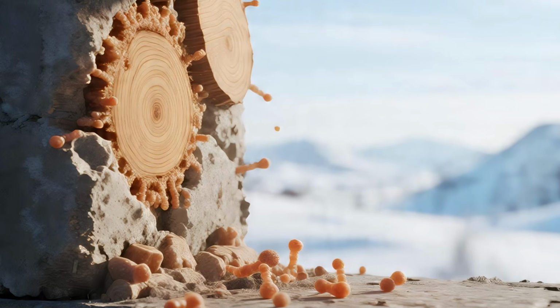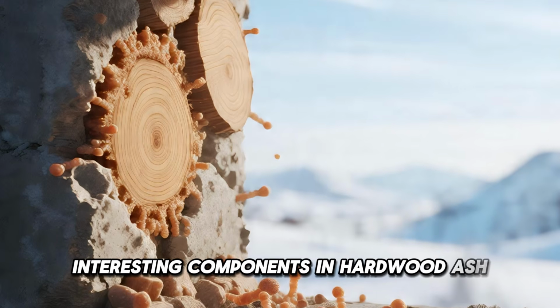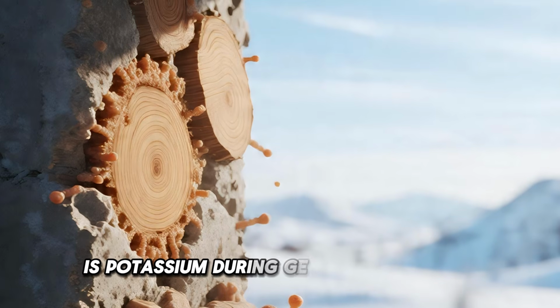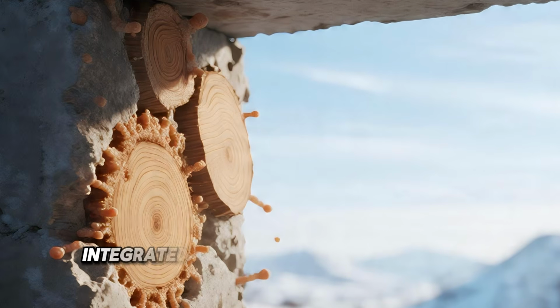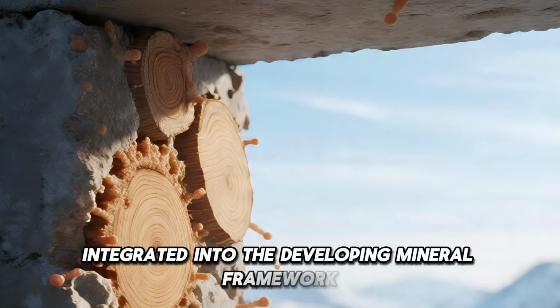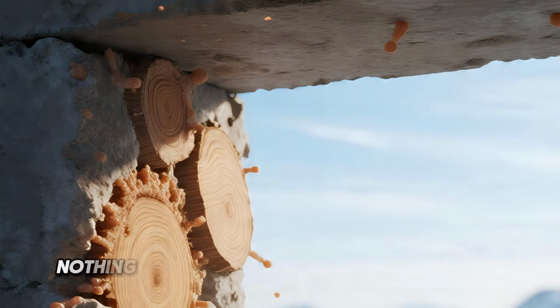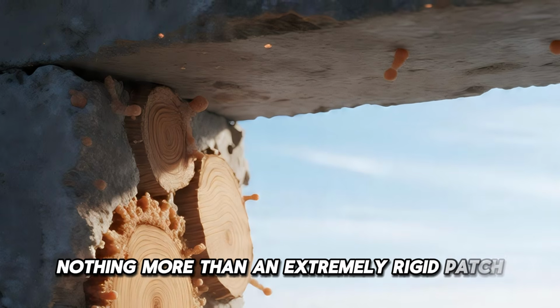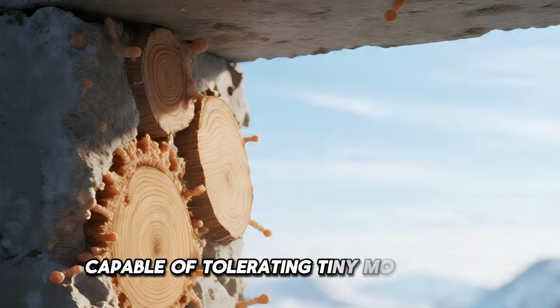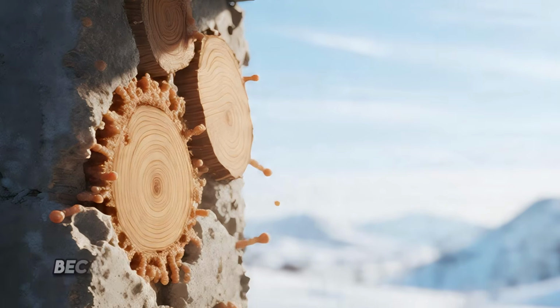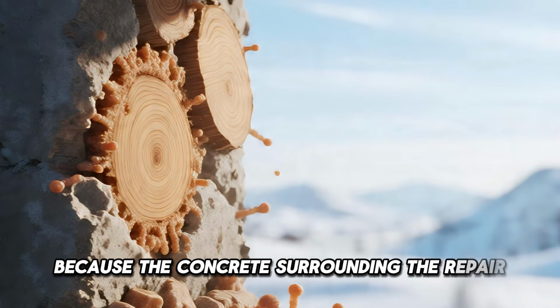And one of the most interesting components in hardwood ash is potassium. During geopolymerization, potassium ions become integrated into the developing mineral framework. Instead of producing nothing more than an extremely rigid patch, these ions help create a structure capable of tolerating tiny movements inside the hardened material. That matters, because the concrete surrounding the repair never stops moving completely.